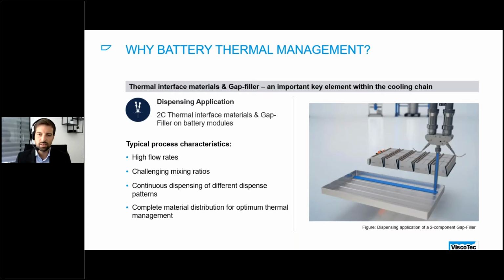Now, to get the best performance out of HV batteries, dispensing and applying of thermal interface materials is an essential task in battery manufacturing and an important key element within the battery cooling chain. To keep the production rates at a high level, high flow rates are a typical process requirement, but furthermore, besides a complete material distribution, a continuous dispensing process and different dispense patterns are needed. As you can see in the illustration on the right-hand side, there's a typical bead dispensing process. Next slide, please.